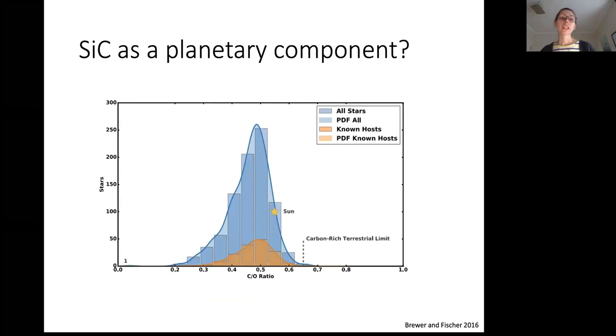Right, and so silicon carbide as a planetary component, as a major building block, is kind of out there and strange. And if you look at a plot of the C to O ratio of stars, so these are observations from astronomers looking at star chemistry, C to O ratios higher than 0.6, 0.65, where you start getting significant amounts of carbon-rich condensates, are not terribly common, but they do exist. And so they represent a really interesting end member of what a planet very different from the Earth could look like.